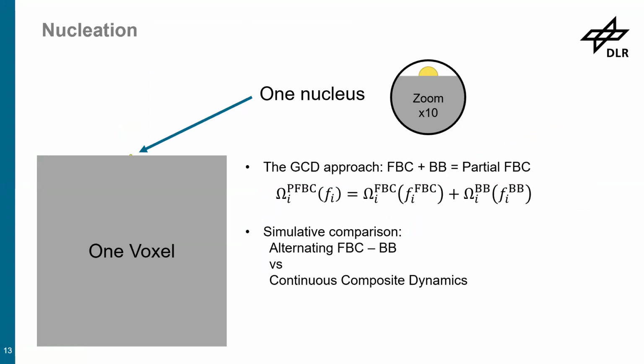So I don't actually take the classical nucleation in here. I just want to show what happens after nucleation has happened. So usually if nucleation has happened, you create one nuclei, and that nuclei is in the order of nanometers, but you actually want to start simulating what the reactions are. And currently in the literature, you either create a whole voxel and make that reactive and say the whole voxel is reactive, and then you have a huge error because maybe only 1% of the voxel is reactive.